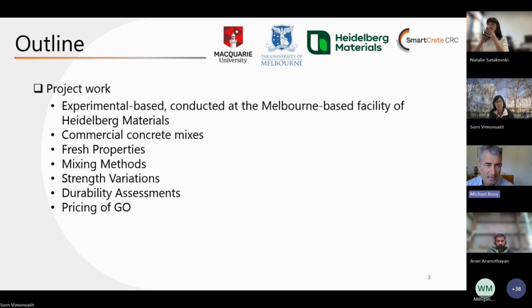So you can see from the outline, the project work was experimental based, conducted at the Melbourne-based facility of Heidelberg Materials. We focused on using commercial concrete mixes. We wanted to see if this would work with concrete material mixers that we were putting out in the market. We were looking at fresh properties, mixing methods, strength variations. We did some durability assessments, but at the end of the day, what we were interested in was, was this commercially viable? Could we realistically expect to see repeatable improvements in 28-day strengths that would be commercially viable? And the idea is that the increase in 28-day strength leads to a reduction in cementitious content, which should allow us to afford to pay for the graphene oxide additive.